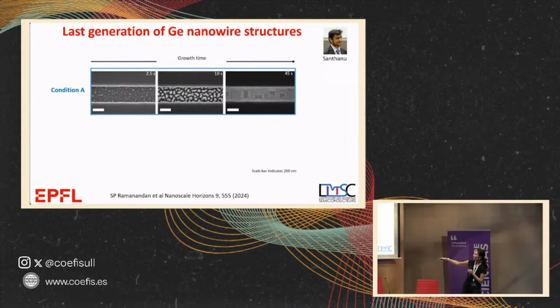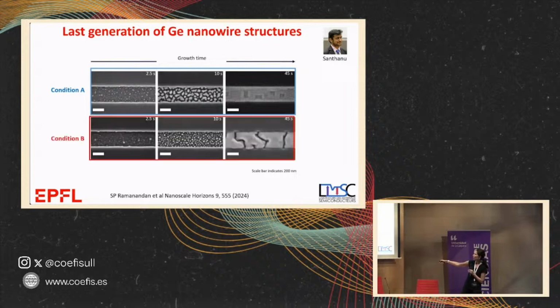If we treat the surface in a different way, in fact, if we don't treat the surface, we also have these islands, and they don't merge. And you see, you don't need to know a lot to think that this will not give you a good material. So this is just by treating the surface in a different way before we start sending the atoms for the growth. So everything is very delicate, and it depends a lot on how we do the nanofabrication and everything. So these are the ones that give the very good results on the transport.